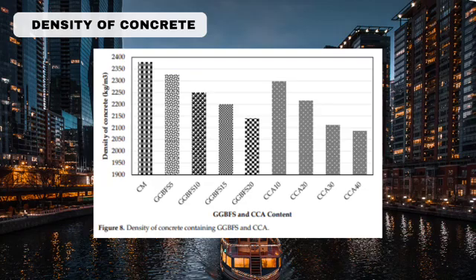The concrete density is 2,325 kg/m³, 2,250 kg/m³, 2,200 kg/m³, and 2,140 kg/m³ with GGBFS levels of 5%, 10%, 15%, and 20% respectively, and 2,296 kg/m³, 2,215 kg/m³, 2,110 kg/m³, and 2,085 kg/m³ with CCA levels of 5%, 10%, 15%, and 20% at 28 days, lower than that of concrete made of PC only.